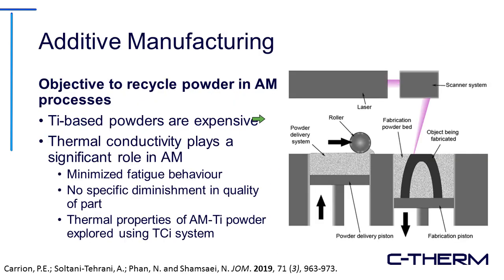During a typical additive manufacturing process, you have your manufacturing bed right here, which is constantly being fed by a roller through which a powder delivery piston will push up powder, and the roller will roll onto the powder manufacturing bed. Using a scanning head on top, we're able to selectively melt the additive manufacturing powder to create your part. And as the roller comes across, you build up your part one layer at a time.